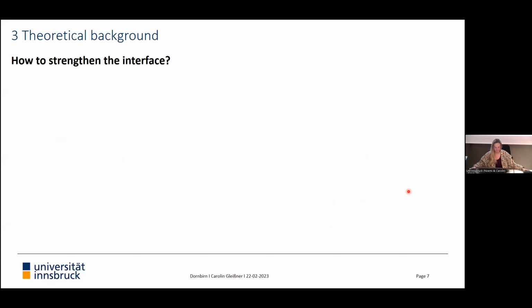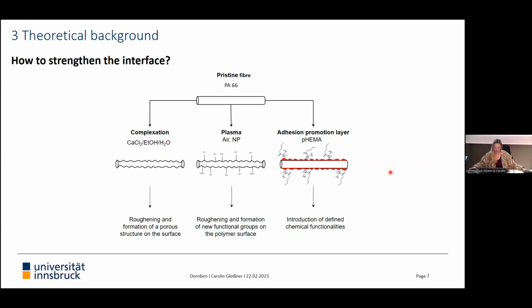So my goal of my study is to strengthen this interface. How can I strengthen the interface? During my PhD, I was looking at 3 different techniques. So I have my pristine PA6/6 fiber or my pristine fabric. And in the first technique, I was using a complexation-mediated solubilization method that uses calcium chloride, ethanol, and water.